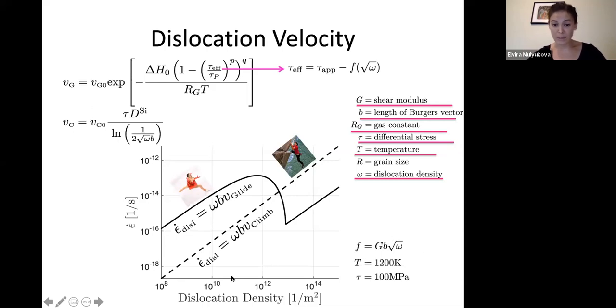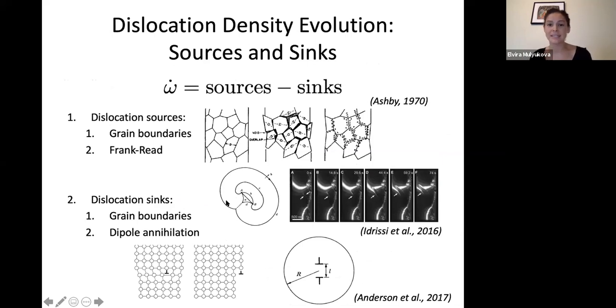All right, and one of the controlling parameters for which of these dislocation motion processes is most important is dependent on dislocation density. So we're going to look more at what dictates the dislocation density in a deforming rock. Perhaps the most common way to look at it, one can also think of it as some form of preserving the deformation history of a rock, is looking at its dislocation density. So we'll be looking at sources, meaning the processes that increase the dislocation density or multiply the pre-existing dislocations, and sinks, so processes by which dislocations may annihilate or recover.